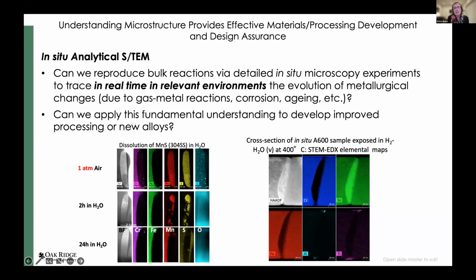And I just have two examples here. One is some dissolution of a manganese sulfide inclusion in distilled water. This is in a liquid cell. These are STEM-EDX elemental images just taken from the material in 1 atmosphere of air in the cell, and then after 2 hours in distilled water.